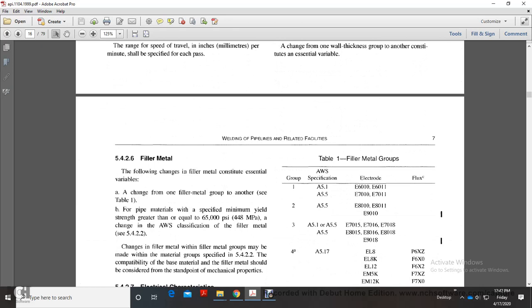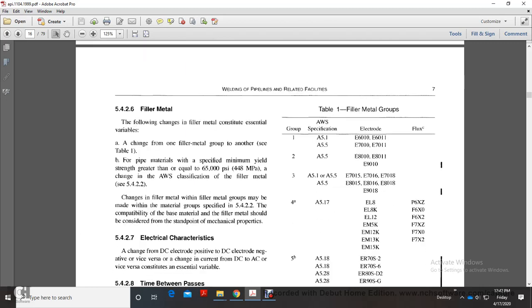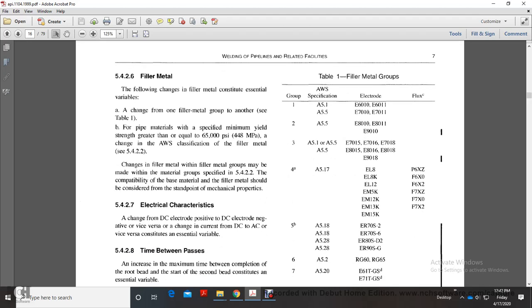5.4.2.6 Filler metal. The following changes of filler metal constitute an essential variable: a change from one filler metal group to another (Table 1); for pipe material with a specified minimum yield strength greater than or equal to 65,000 psi, a change of AWS classification of filler metal. Changes within filler metal groups may be made within the material group specified in 5.4.2.2. The compatibility of the base metal and the filler metal should be considered from the standpoint of mechanical properties.